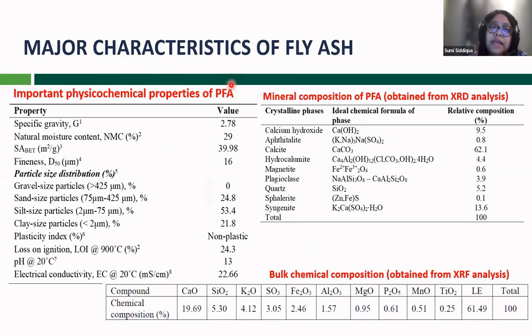And this one, we have the general elemental properties coming from the geotechnical laboratories: specific gravity, surface area, fineness, grain size distribution. As you can see, the sand-like particles are 24.8%, so almost 25%. Silt-like particles are around 53%, and the clay size particles are around 22%. Also, we have looked into the loss of ignition. pH value is 13, that is more on the alkaline side. And then we have electrical conductivity of these properties.